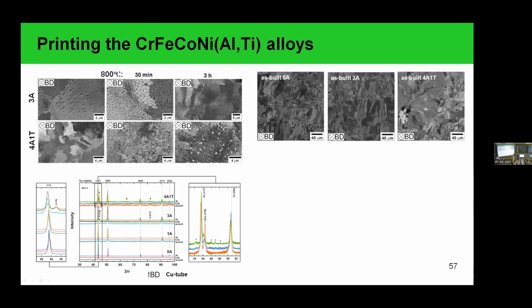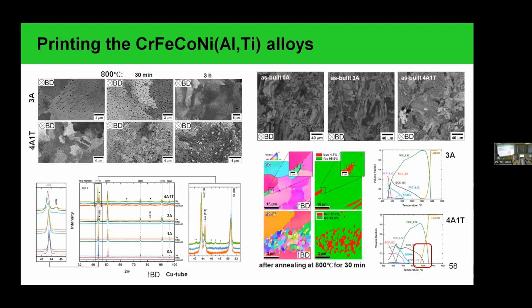And also we observed the difference of the microstructure for our materials with or without titanium. Materials with aluminum only demonstrate generally the same microstructure as the four-component system, typical for the face-centered cubic structure. But in case of the material with titanium, we observed the zones enriched with small grains and those with uniform grains. Analysis of these zones after heat treatment demonstrates these small grains consist of the BCC and FCC phases. So there are small-size grains of the one and of the two phases. In case of the material with aluminum, we see the formation of the new phases in the already formed grains.